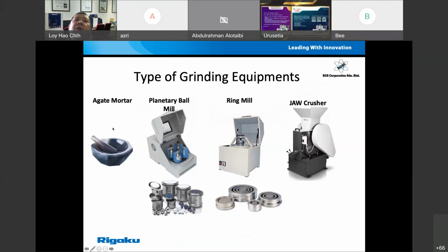The very conventional one is an agate mortar. If you can grind, or pound, your samples with the agate mortar until the required size, then you can proceed with the XRF. Then the next will be planetary ball mills, where you put your samples into vessels, then you load it with balls of different sizes, then the vessel will spin. During the spinning process, the balls will hit the samples, and the samples will also knock on the wall, so the samples will get smaller and smaller.